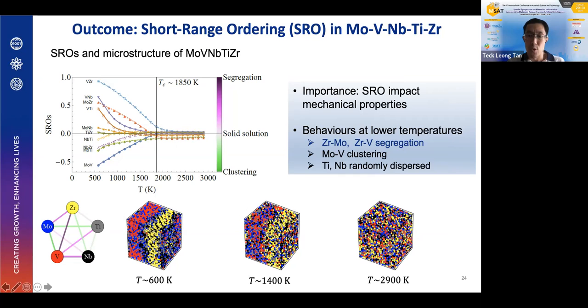On the right, this is a box of various atoms and atomic configurations. There will be 5 different colors for 5 different elements. You can see that at high temperature, all these atoms are randomly arranged, so we call it the solid solution phase or the disordered phase. But as you decrease the temperature, there's increasingly more segregation. The vanadium atoms in red and the zirconium atoms in yellow phase separate from each other, and this phase separation becomes more and more prominent as we go to lower temperature.